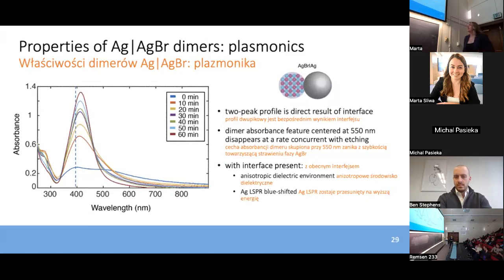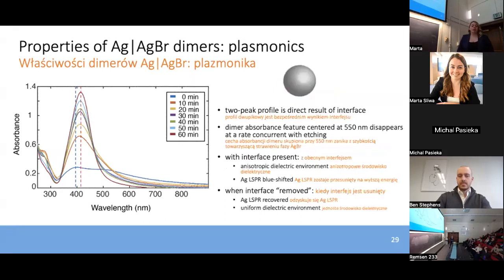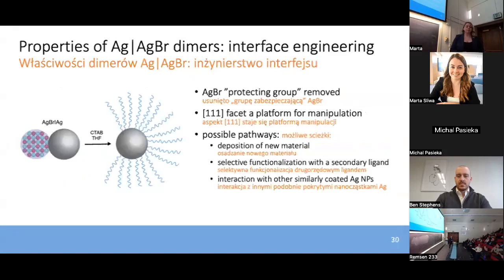So this is due to that anisotropic, or in other words, uneven or unsymmetrical dielectric environment that that silver particle is facing or experiencing with the silver bromide on one of its facets. When the etching process continues and that silver bromide is removed, we recover a uniform dielectric environment, so symmetrical all the way around that silver nanoparticle. The plasmon peak shifts to a higher wavelength or lower energy, and again corresponds with the plasmon resonance for a standalone or a solution of isotropic silver nanoparticles in this size regime.